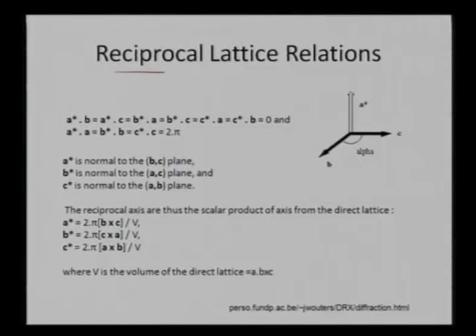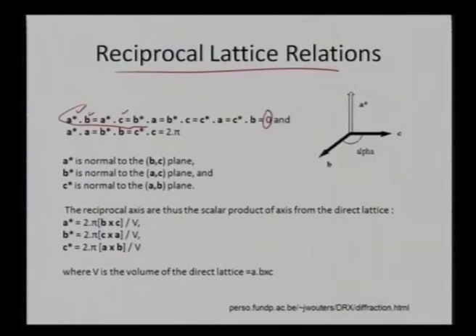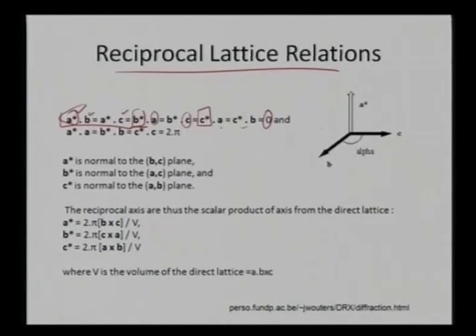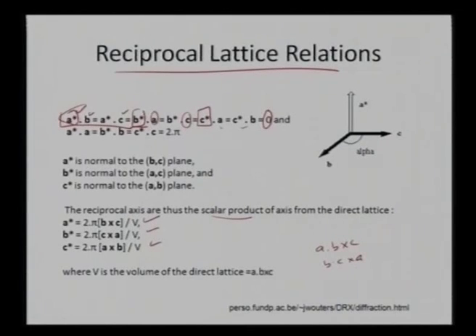I have this g vector corresponding to the 1/d vector in real space. What is so good about the reciprocal lattice is that I am eliminating one dimension while still being able to mimic my real lattice, which assists in visualizing things much more clearly. Coming back to the relations of reciprocal lattice equations: a* · b = a* · c = 0, meaning the reciprocal lattice spacing is perpendicular to the original axis. Similarly, b* · a = b* · c = 0, and c* · a = c* · b = 0, so all these are perpendicular to the other two axes.